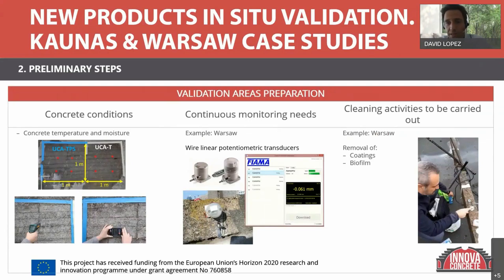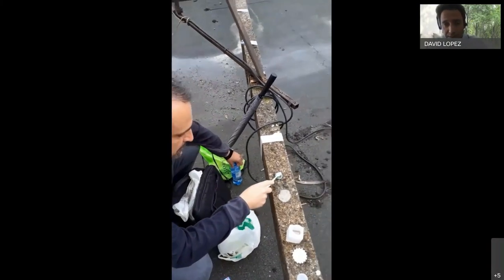Before the application, we need to conduct some preparation of the surface or some preparation regarding certain measurements that need to be undertaken. And one of the things that we do is analyze the concrete conditions. It's important to know the temperature and moisture of the concrete surface before applying the products. In some cases, in the case of cracks, it's important to have a continuous monitoring previous to the application of the products. In our case in Warsaw, we did it with wire linear potentiometric transducers that were installed by Rina, and it's just to know how the product behaves in the future, but having the knowledge of the history of the crack.